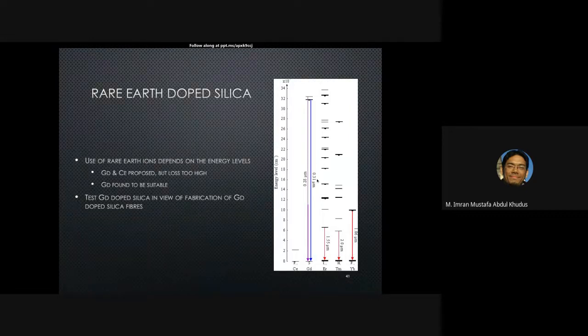The reason you want to put something like a rare earth dopant rather than something like zinc oxide is that zinc oxide is a semiconductor, and it doesn't blend really well in glass. So typically we put something like rare earth doped silica. As comparison, you have erbium doped, thulium and ytterbium. These are more commercial and the normal kind of infrared radiation that we are most used to. The ytterbium doped is mostly used for high power lasers, right?